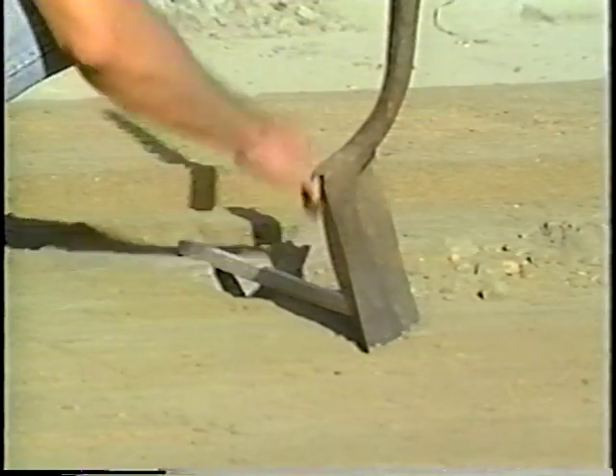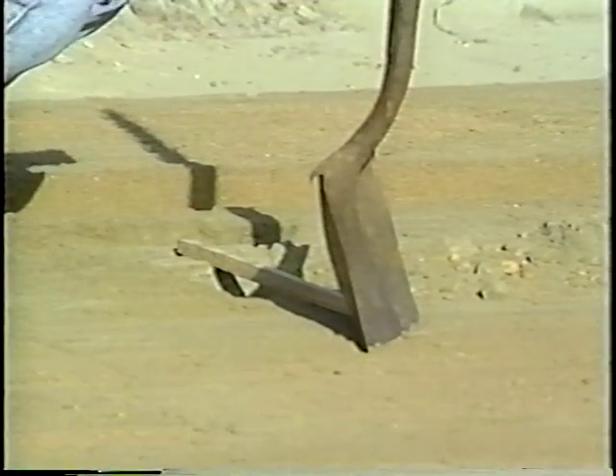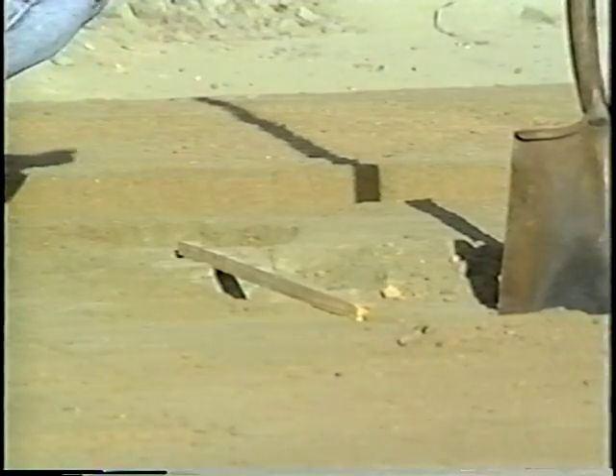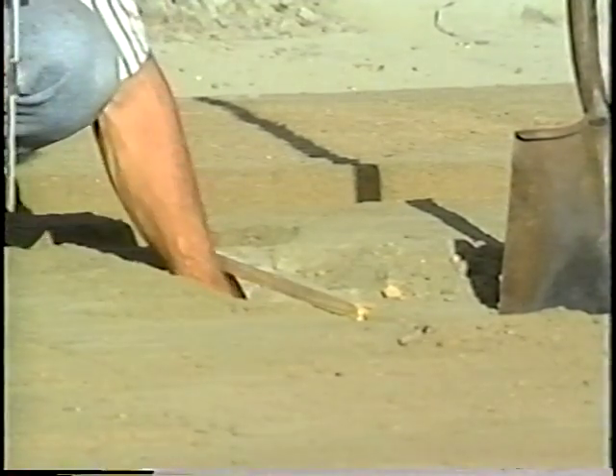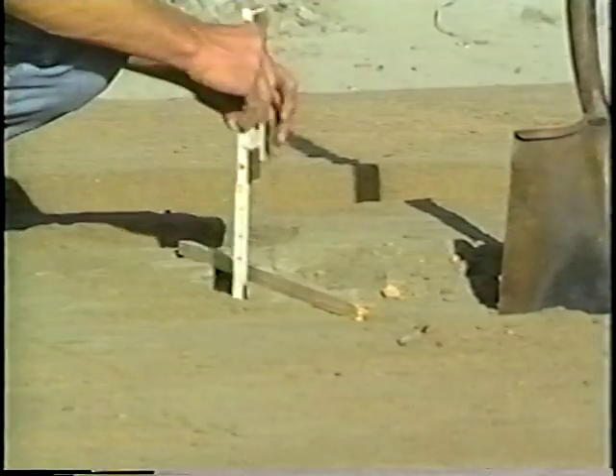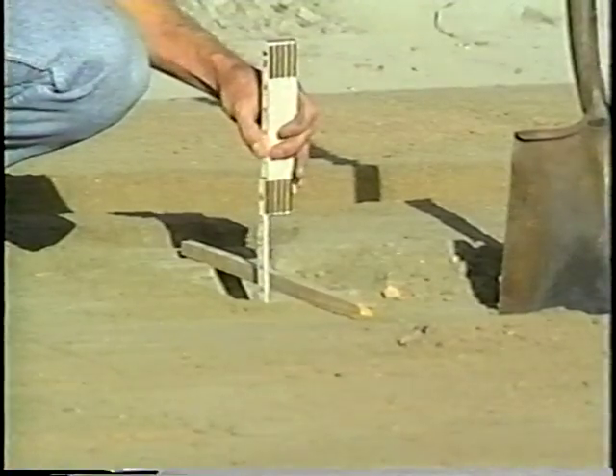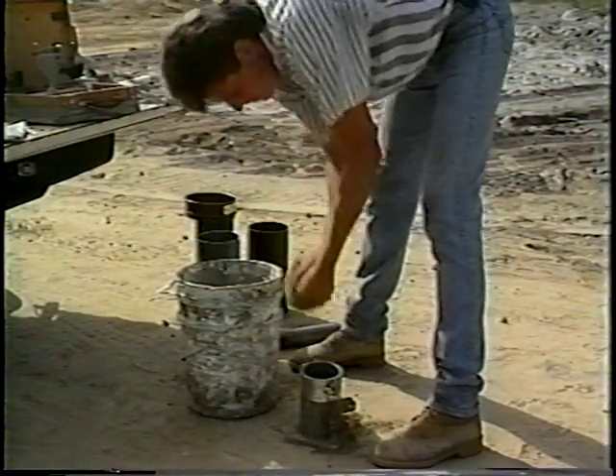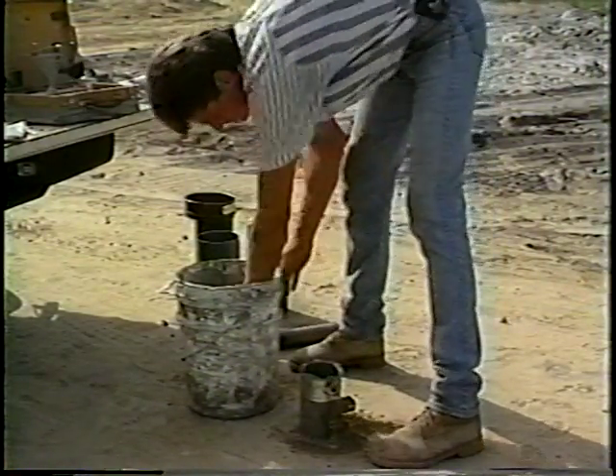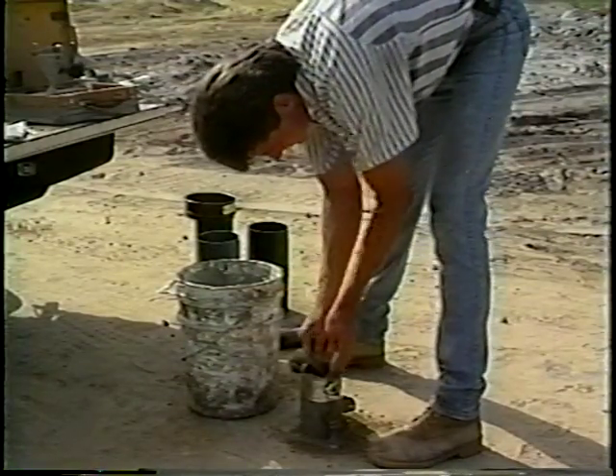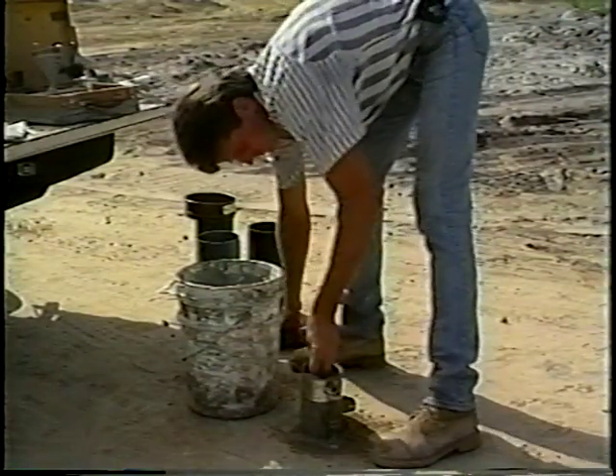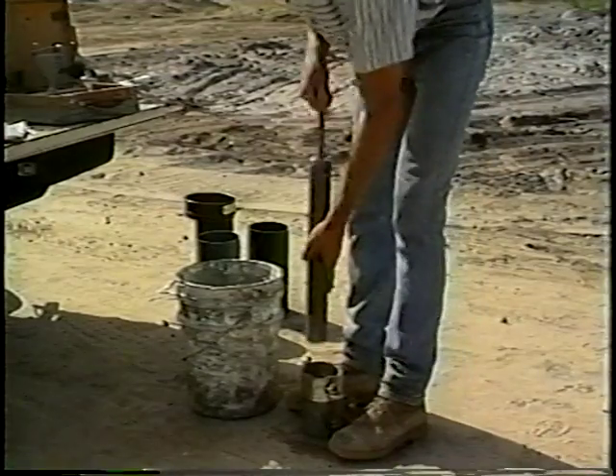Testing for thickness acceptance requires 3-inch minimum diameter holes drilled or dug after hard planing. Thickness is determined by measuring the depth of soil cement in the holes. For mixed designs prepared by the strength design method, field strength testing samples are obtained of mixed soil cement material and formed just prior to compaction.